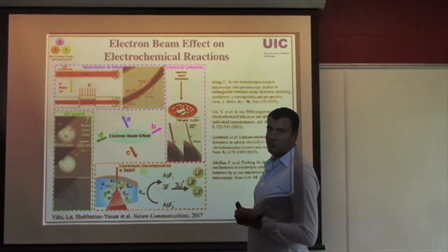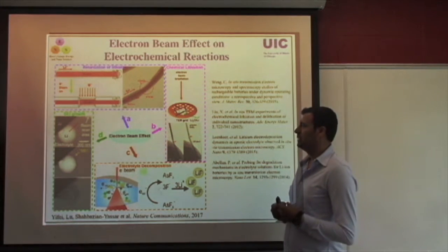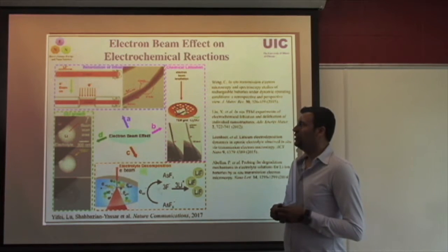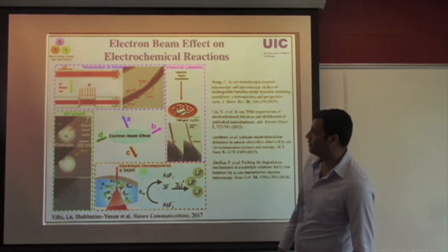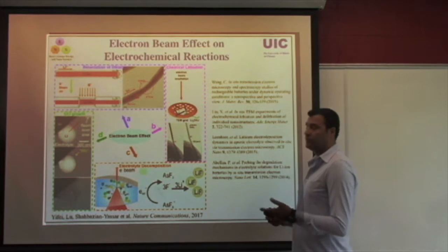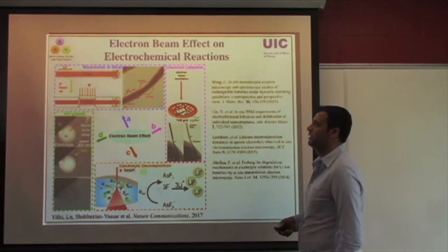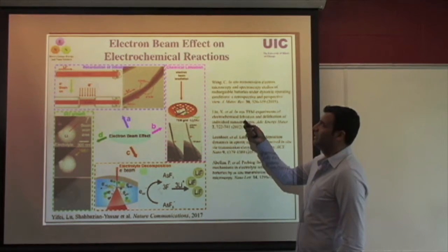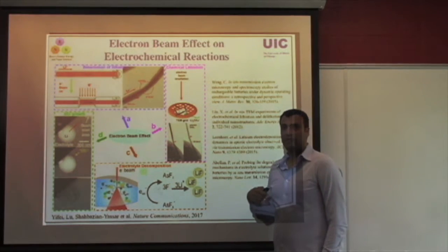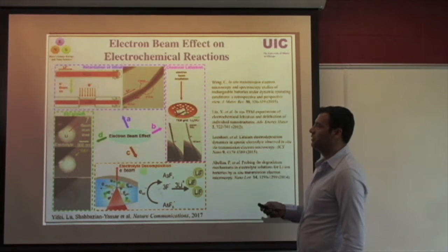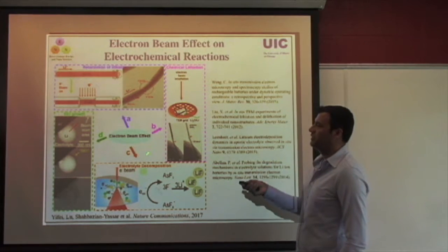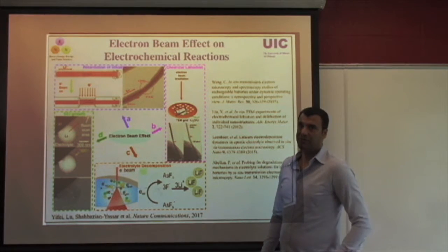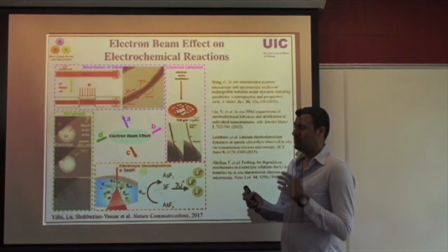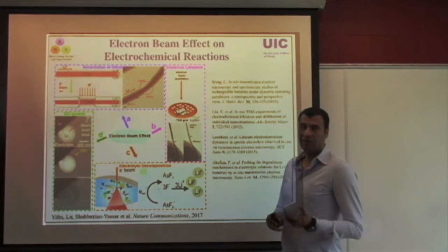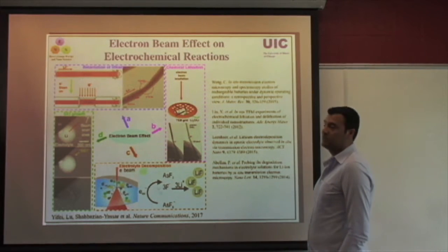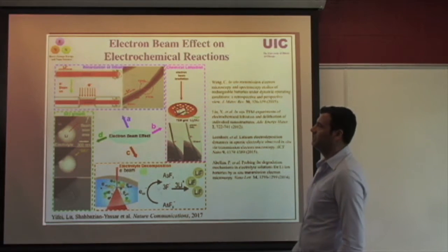One of the important considerations when you use electron microscopy to study electrochemistry or electrochemical reactions is to be mindful about the artifacts that could be produced during imaging or spectroscopy analysis. We typically call this electron beam effect. It can have some knock-on damage. It can have some sort of radiolysis. So there are a variety of issues that could be associated with the electron beam. We need the electron beam for our imaging or chemical analysis, but at the same time, it can have some artifacts and maybe counterproductive effects on the analysis we want to do.